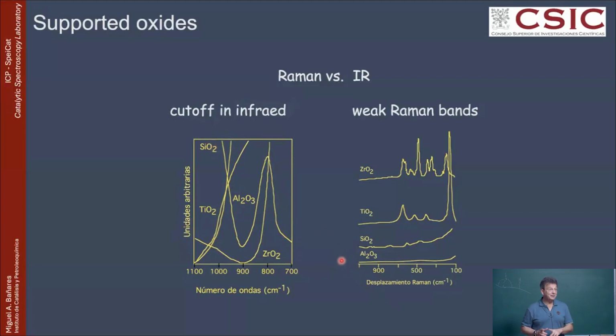Now, the Raman spectra of these oxides is different. It's very weak, and when you have sharp peaks, they are at relatively lower frequency and their intensity is not that high. Titania or zirconia, you will see bands below 700 wave number, but this region here, which is very important for the bridging oxygens and terminal oxygens, is still exposed. Some bending modes will not be visible here, like a vanadyl bond will be around 1000, but then the bending around 200-300.